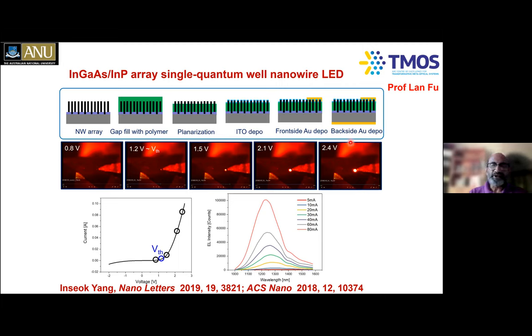You can see the IV characteristics showing diode-like behavior, indicating again that Insu's hard work really paid off. And the higher the amount of current you're injecting, the higher the amount of light coming out of these. And again, you don't see any narrowing of the line width. In fact, you can see under the probe here a very bright light coming from these at the higher currents. Even visually, you are able to see these things.